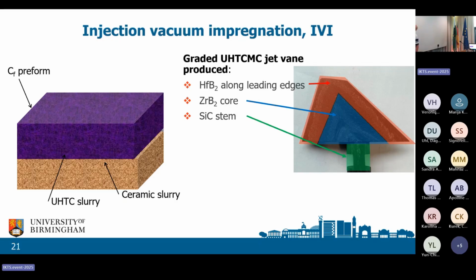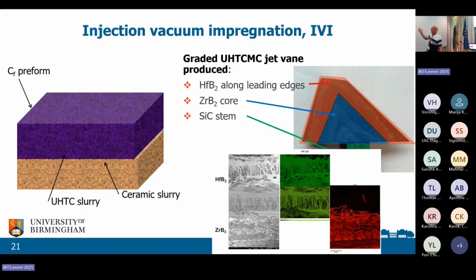But now you can have one material, let's say hafnium diboride, that gives us 3000 capability on the outside. Zirconium diboride, that gives us 2000 degrees centigrade in the middle. And then you can have something else entirely, like silicon carbide, in the little stem. That's all one piece of fiber. It's no joins. It's all one piece. So you can put what you want where you want it. As I said, you don't get a hard interface. So this is the hafnium, this is the zirconium. And you can see in this region here, you've got both and they're nicely mixed. So you don't have a hard interface.